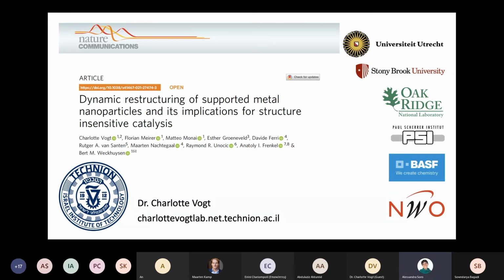During your in situ TEM measurements, did you also observe the lattice expansion contraction phenomenon for other particles, for example, particles of different sizes? Yeah, so we focused on the nanoparticles that were about 5 nanometers, so we recorded the most images of those nanoparticles because they had very clear lattice fringes to start out with. But there was always, to a greater or lesser extent, a degree of restructuring.